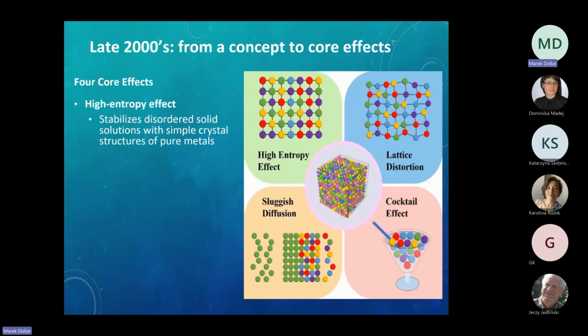Now, the high entropy effect. The high entropy of mixing resulting from the presence of 5 major elements stabilizes what we call disordered solid solutions. I will show you an example in just a moment, with very simple crystal structure, equivalent to pure metal structures. By having elements with different atomic sizes, we have severe lattice distortions. There is an enhancement of strength, but at the same time, it slows down dislocation motion, which is responsible for plasticity, for ductility.